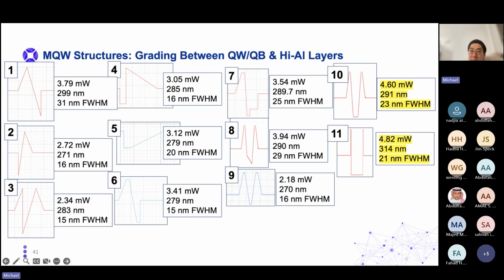And what I found in the end was with these two structures, where we have our quantum barrier, we grade up to this high aluminum layer, grade down immediately, and then grow a quantum well, and then grade up this high aluminum layer, grade down, and grow a quantum barrier, versus another where we just immediately change the flows and don't grade. So these two ended up being the best. The one with the grades worked better for thinner quantum wells, and the one without grades worked best with thicker quantum wells, because thinner quantum wells emit at shorter wavelengths, and we wanted to target the germicidal wavelengths. We stuck with structure number 10 here.